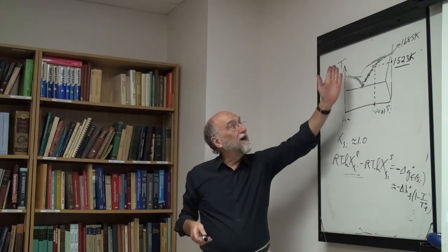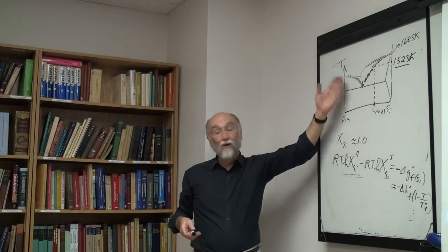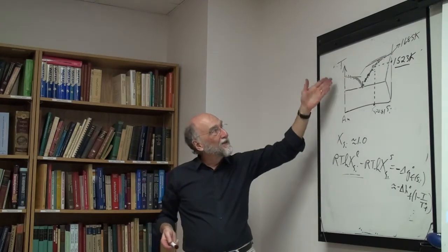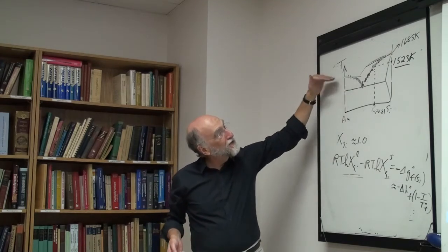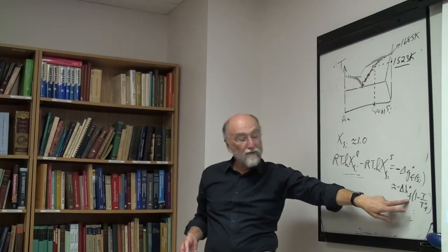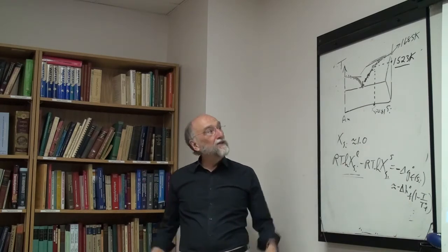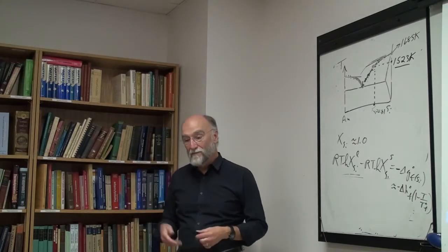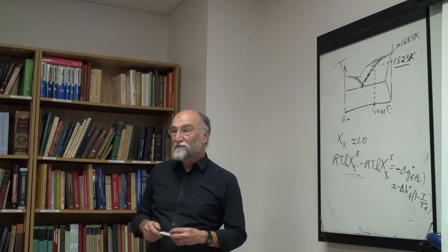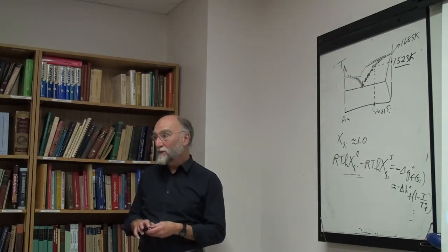And if it's way, way higher, then you probably have solid solubility, or maybe there's something wrong with the phase diagram. But the zero solid solubility line is calculated only from the heat of fusion and the melting point. You don't need any other information to get it. So you get a lot of information just by looking at those two limiting slopes. I'll give you a better equation for it in the future. Kind of clear what I'm doing?